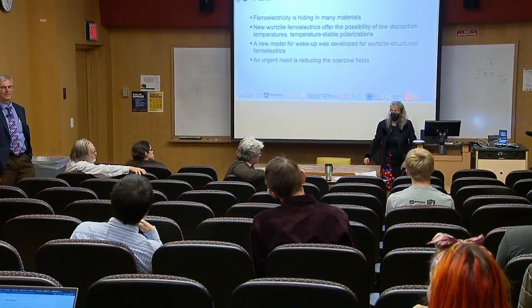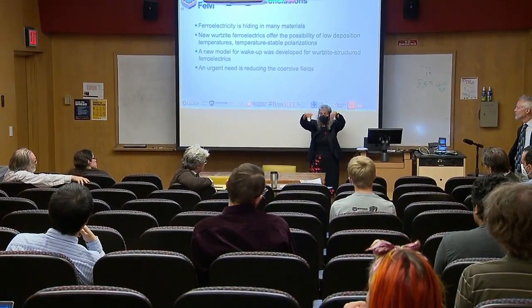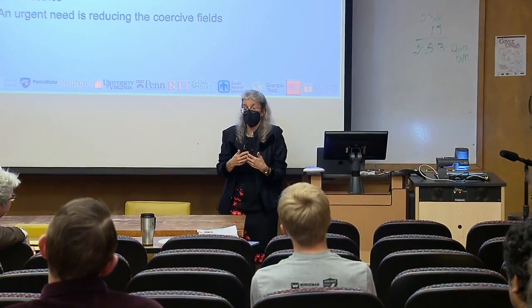Okay, so imagine that we start the material all with the polarization in the down direction. Almost always in material science, if you want to make any change, it's easiest to do that if you have some nuclei pre-existing. Very often, nucleation provides a big barrier. And so the polarization reversal process is typically a nucleation and growth process. And I start with no nuclei. So I start with everything in one orientation. The first couple polarization attempts to run a polarization reversal cycle, I think what we do is make the nuclei.